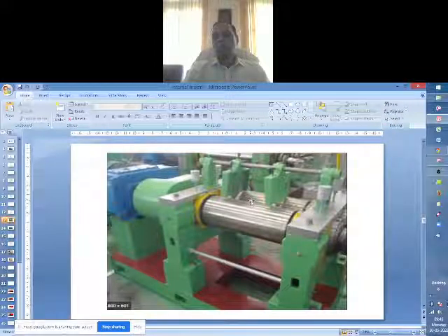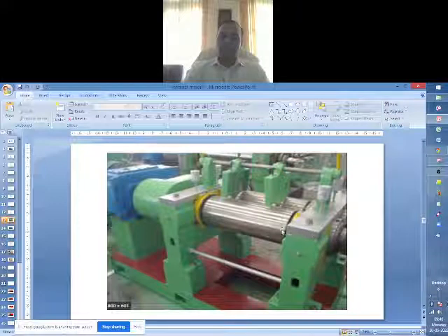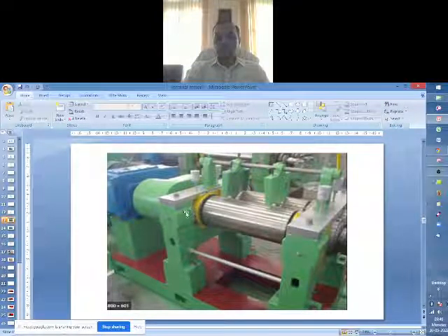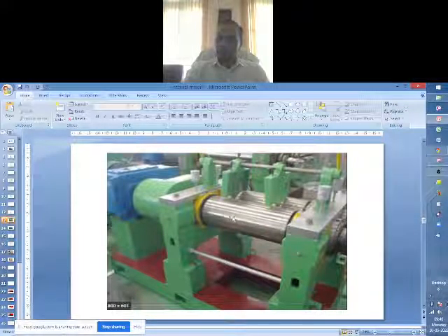So when you pull in, you have some material there which is kind of incompressible. It will flow, but the volume will not be reduced in that sense. Because of this, there is going to be huge stress on the roll, pushing it outside. In that stage, the shaft on which it is fixed, or the bearing on which it is resting, should not be damaged. So there is a safety mechanism here, a plate mechanism, so that when the force on the rolls is too much, beyond the limit, that mechanism will fail and the roll will move a little far away, creating more space there.